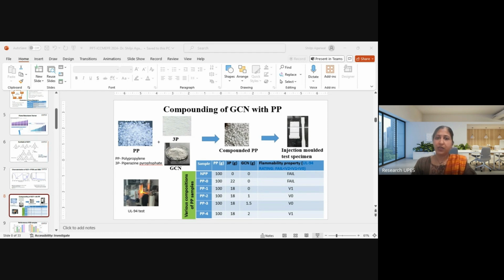So here in the table, you can see the composition. NPP is the neat polypropylene, which is pure polypropylene. In PP0, we added polypropylene and piperazine pyrophosphate, 22 gram. In PP1, it was 18 gram. And in PP2, PP3, and PP4, along with the 3P, that is piperazine pyrophosphate, we have added GCN 1 gram, 1.5 gram, and 2 gram.